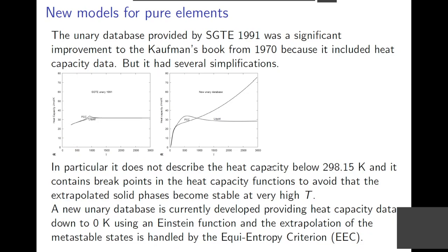In the new unary database, which is being developed right now, there are two big changes. One is that one includes heat capacity data down to zero Kelvin. So here one should have zero heat capacity. If you extrapolate the current unary to low temperature, you would normally find negative heat capacities, which is not physically realistic. And to avoid the breakpoint at the melting temperature, one introduces a modeling criterion that a solid phase with higher entropy than the liquid must not become stable. So that is a kind of theoretical limit on the stability of the solid phases.